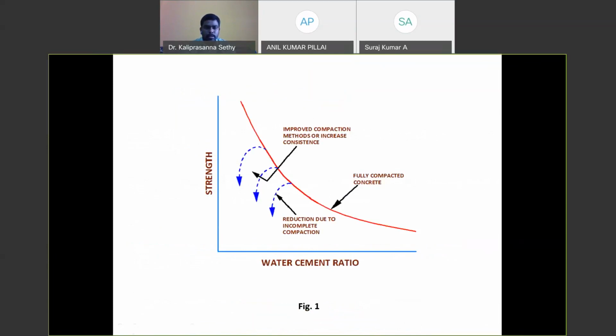as you can see from this figure, this is nothing but Abrams' law, the water cement ratio law. This is plotted between water cement ratio and strength, and the curve is valid only in the case of fully compacted concrete. But at the time of placing the fresh concrete at the site, in the formwork, if we don't take care of the compaction, the strength may drastically reduce. You may not find this curve in this position; it will drop to this position, and the strength and water cement ratio you will find will be different than what you achieve for fully compacted concrete.